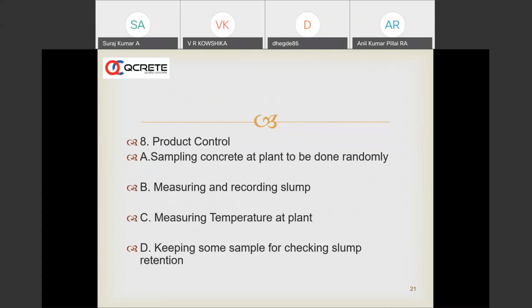When we are talking about product control, we have sampling done at the plant randomly. Some of the ready mix companies, like our company, check every truck before sending. As soon as the production takes place, we take a sample and check it in most of the trucks, and then measuring and recording the slump is important. We also measure the temperature at the plant, and then we check the slump retention.